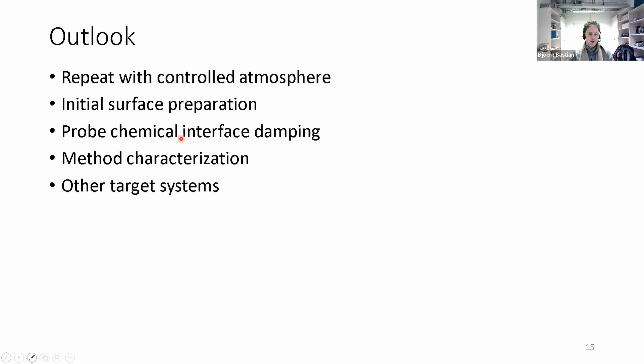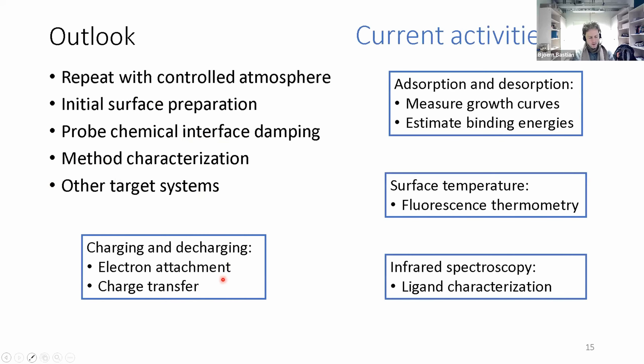This was really our first real life system. We're still mainly in the phase of method development and characterization and seeing what are the next target systems that we can do to step-by-step increment our experimental capabilities. I think I have time to show a little bit what we've been doing last year, which is to understand in detail the charging and discharging to have control of the charge state of these particles, to start becoming quantitative with understanding adsorption and desorption dynamics to finally hopefully estimate binding energies, which crucially depends on surface temperature. We had a first partial success to use fluorescence thermometry to really measure the surface temperature in situ. We would like also to move forward from visible spectroscopy to infrared spectroscopy, which is directly sensitive to ligands at the surface.